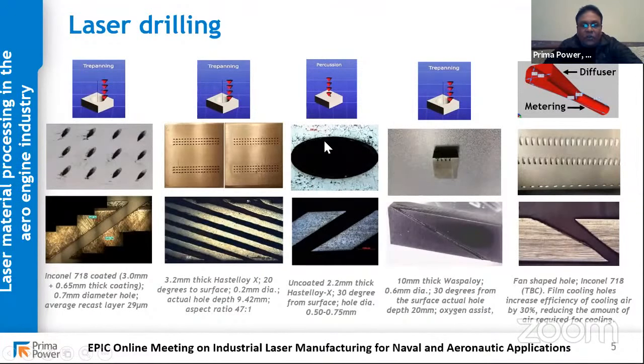Again, you can see the top of the hole is very round. And this is a cross section, again with very little taper from top to bottom. So that's another example. Typical diameter is 0.5 to 0.7.